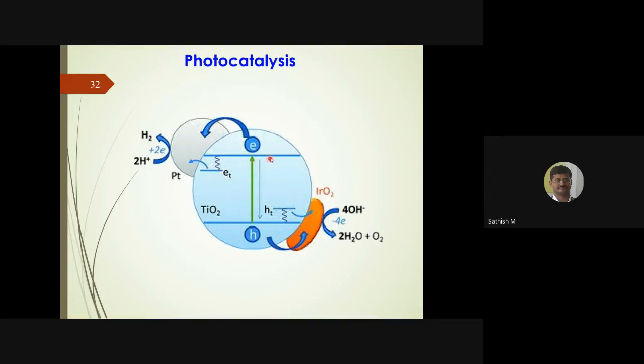Now this electron is no longer available for this TiO2. It moves to the platinum. Because of this, the recombination process can be avoided, so that the efficiency of the process could be increased. Once it goes to the platinum surface, it can take its whole time to reduce the H+ ion to hydrogen. Similarly, you can also take back the holes produced in the valence band using some catalyst. Platinum or iridium oxide could be used as a co-catalyst to capture the holes, while platinum, gold, palladium, ruthenium, or rhodium could be used to take the electrons.